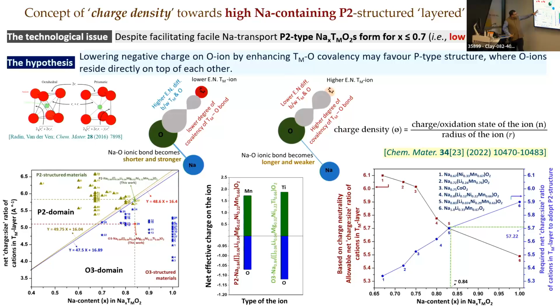Now, when we looked at the lot of P2 structured material reported in the literature, we could actually segregate them into two domains based on the charge to size ratio of the cation combination in the transition metal. So those having a lower charge to size ratio fall in the O3 domain. These are all O3 structured, and with the higher charge to size ratio for a given sodium content, these are all P2 structured materials. And in fact, one can draw a line separating these two domains, and one can get an equation for the line.